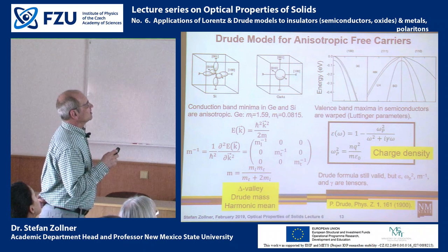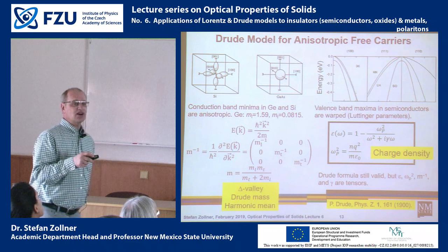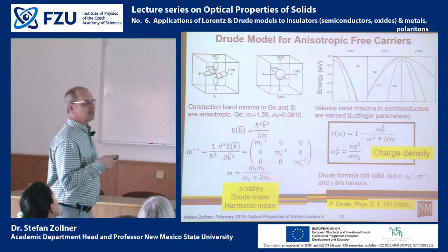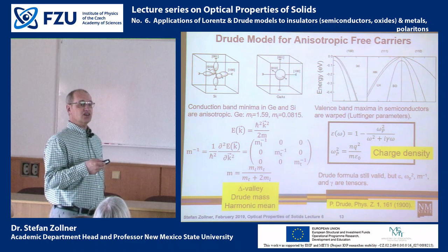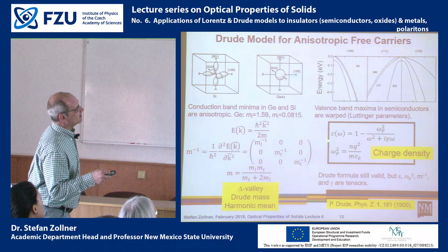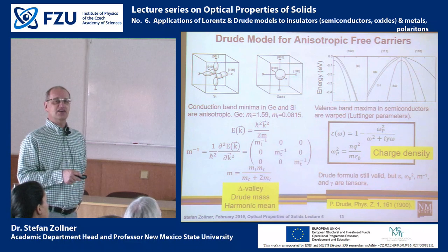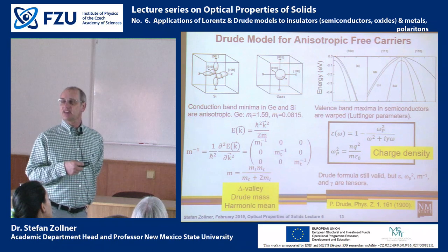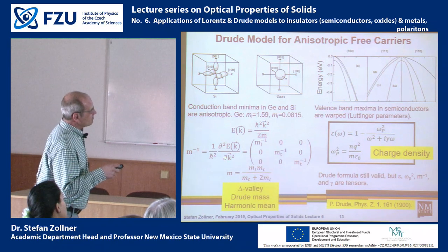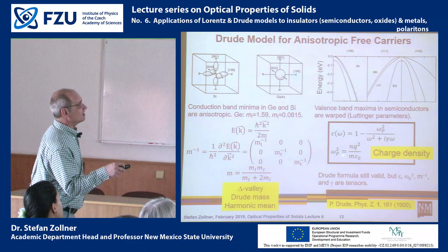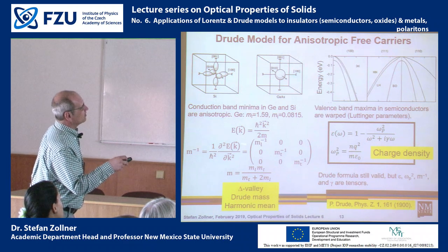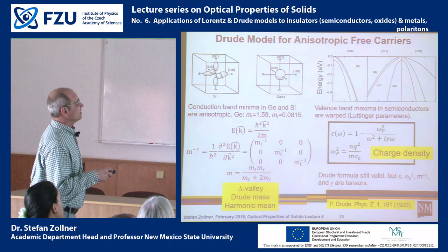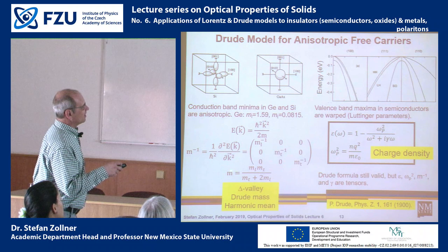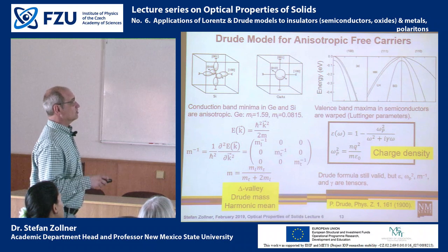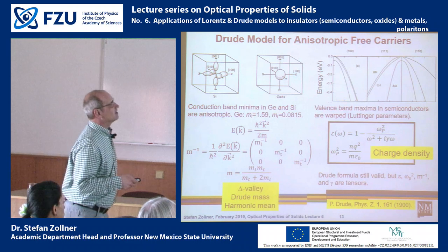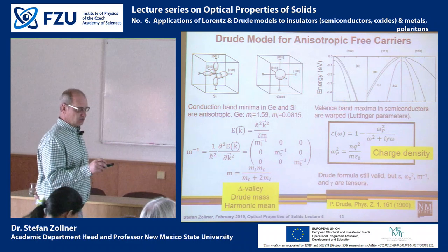I'm sorry, the valleys are anisotropic, but silicon as a material is still cubic. And because silicon as a material is still cubic, the dielectric function is still described by a number, by a function, not by a tensor. However, the mass which enters here in the plasma frequency comes from an anisotropic valley, and therefore we need to take the harmonic mean of the three masses in order to describe this semiconductor with the Drude model.